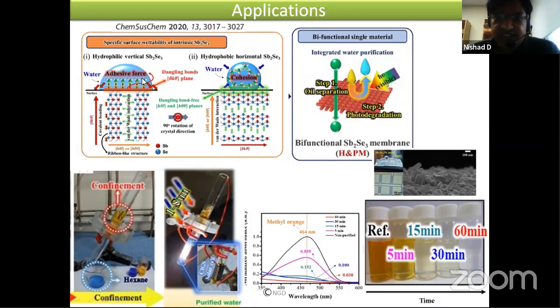So what we can see is that with change in the facet structure, you can actually control the hydrophilicity or hydrophobicity. So our main purpose was to make a bifunctional membrane, which can be utilized for both oil separation as well as the photodegradation of the dyes. Therefore, we developed this material on a platinum mesh, and you can see that these structures are nanorod structures, which are having both surfaces now. So we combined this into a device, a simple device where we utilize this mesh on which we have grown the antimony selenide.